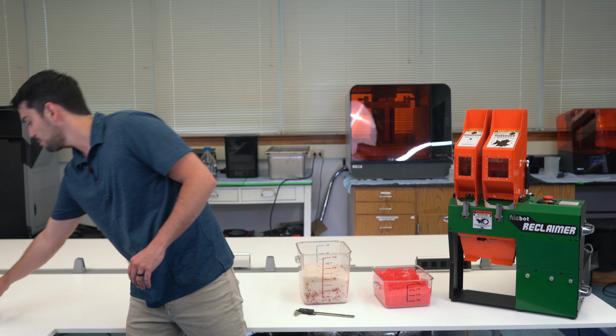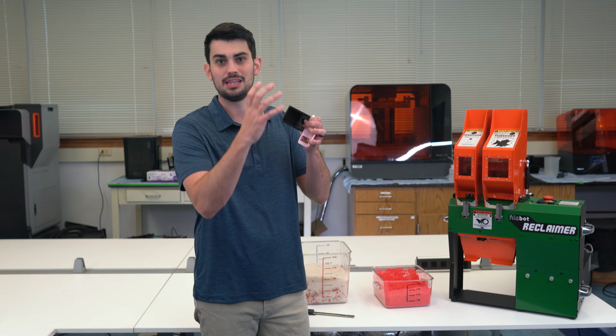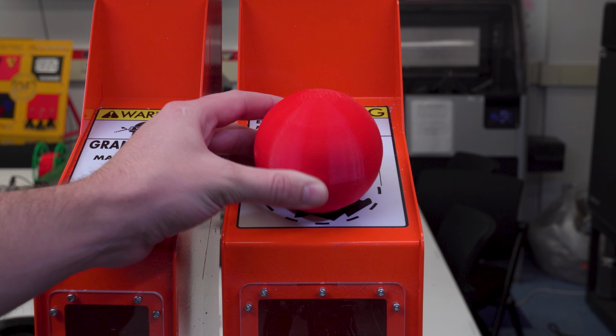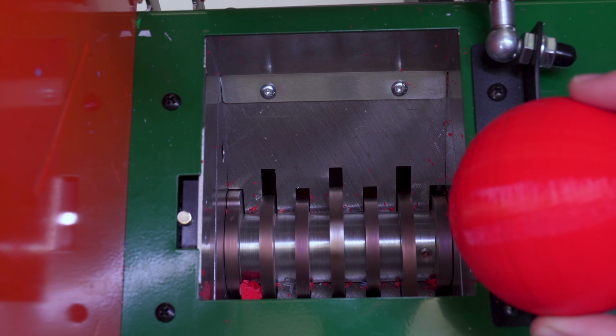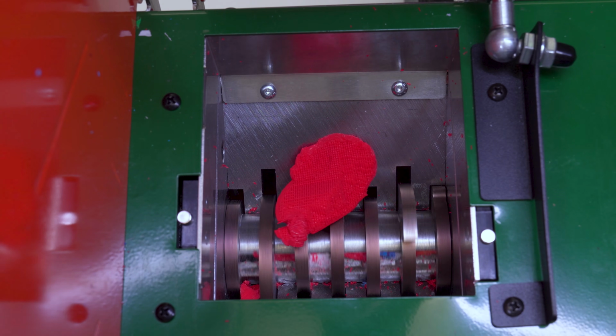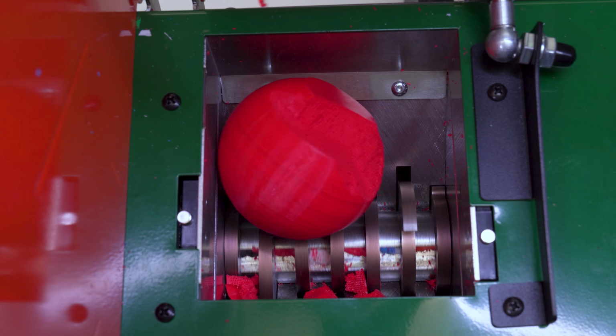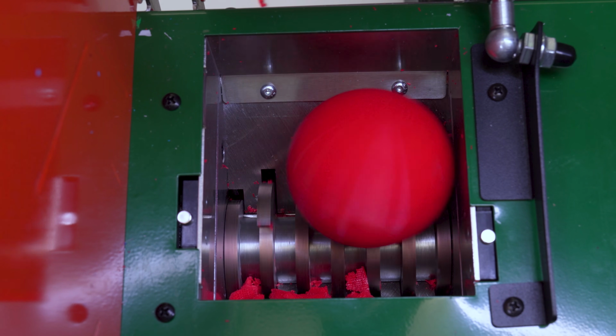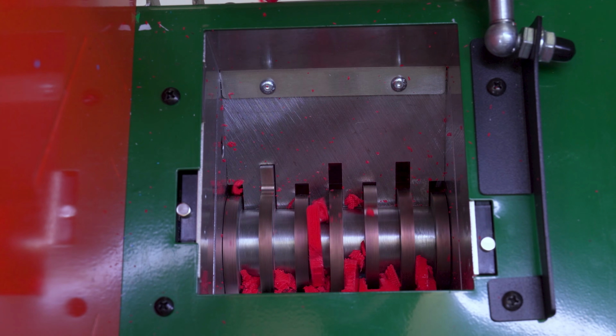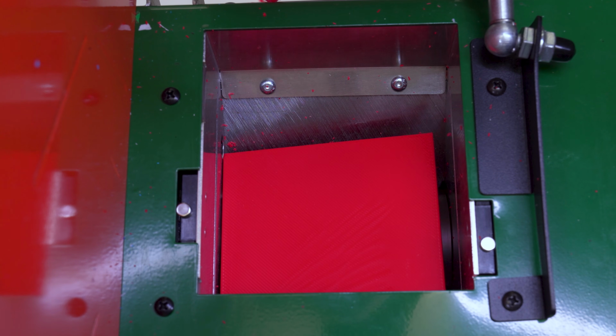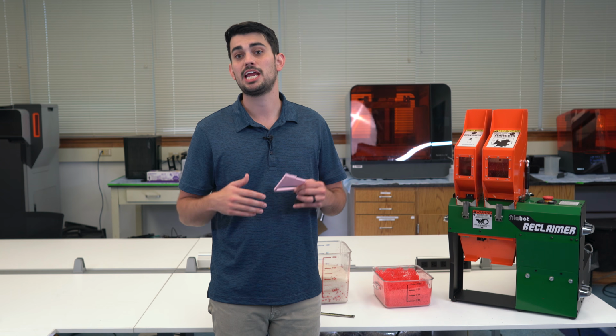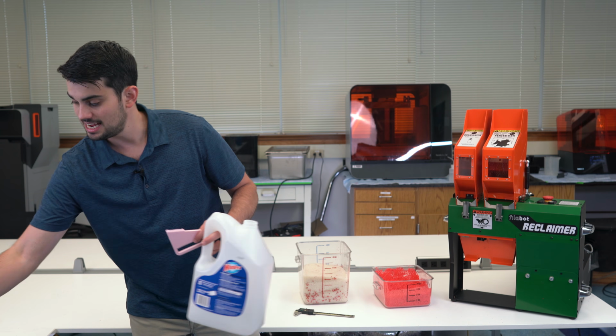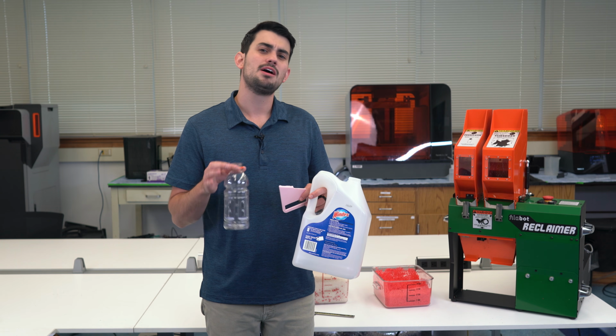One more issue that I want to discuss with the reclaimer is that even when the parts are smaller than that 3-inch diameter, their shape can affect the ability of the shredder's blades to grab a hold. Intricate geometries are the easiest to shred, as there's usually ledges and surface texture that allow the blades to suck the material in. Round and flat objects are more likely to bounce around inside the chamber. When you run the reclaimer for a while, you can spot the parts that will shred well and those that won't. These limitations of size and shape make it almost impossible to grind up common household recyclables, such as cleaning containers and water bottles. We will discuss how I attempt to recycle these later, but I don't want to leave the reclaimer on a bad note.